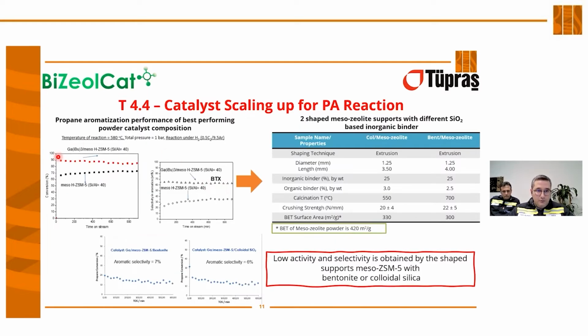On the right side you can see the powder material performance for the reaction. To reach this performance, we shaped the mesozeolite with different silica-based binders. One was prepared with colloidal silica, another was prepared with bentonite.